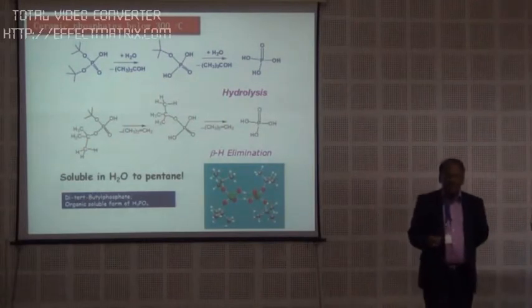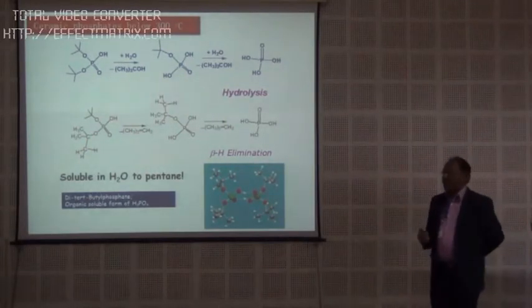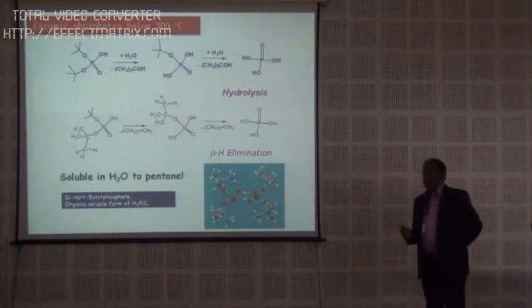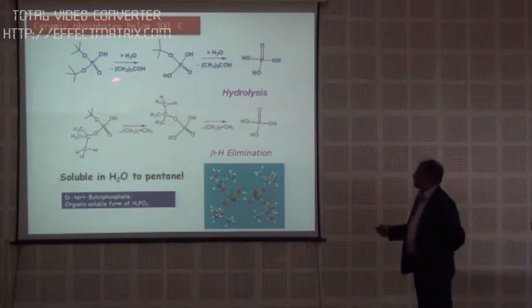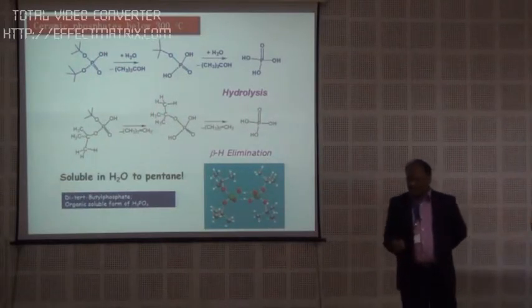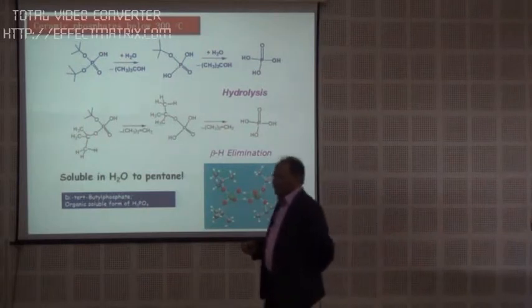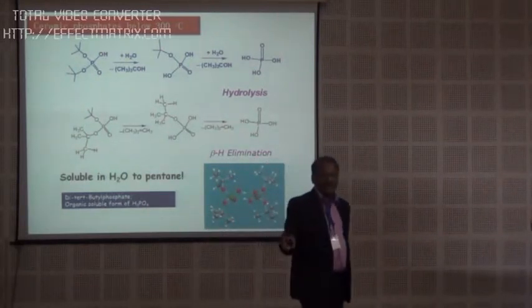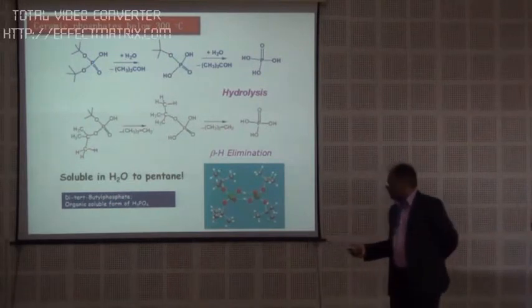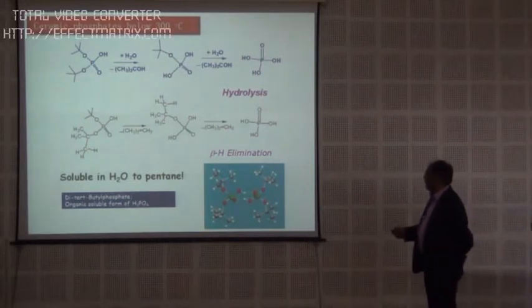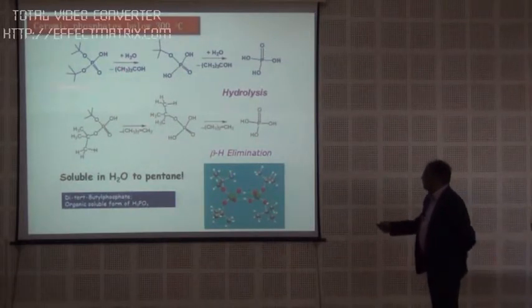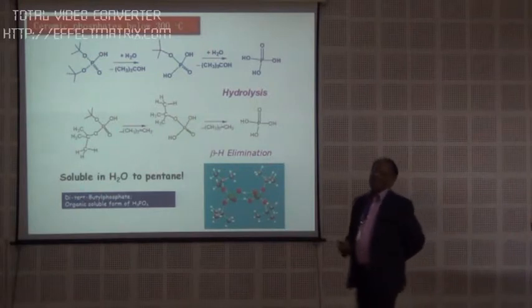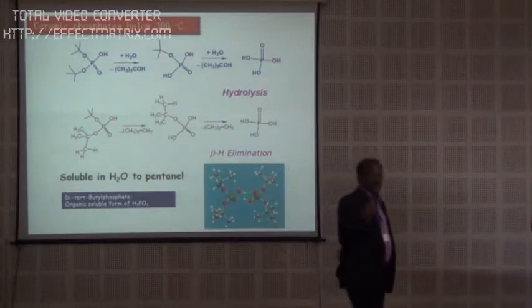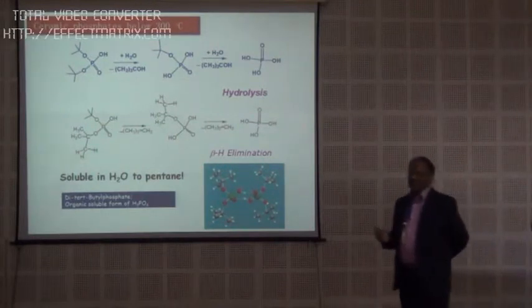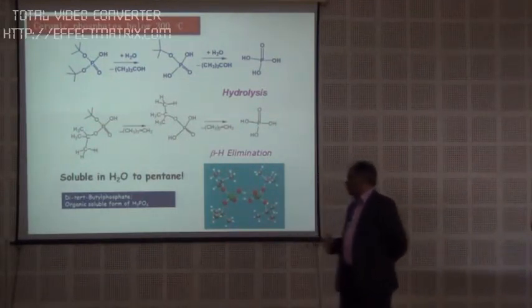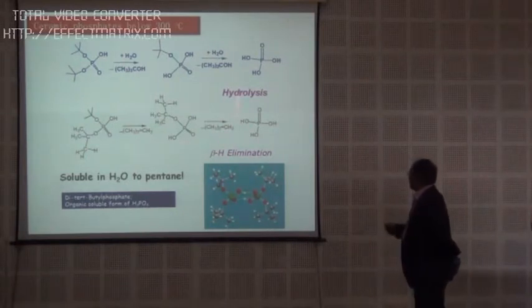Years ago, we recognized that there are compounds in the literature. In fact, a paper published in 1960 by Harris and co-workers in the Journal of the Chemical Society talks about this one particular compound, among many esters that have been described in the paper. This compound was described as useless because you make it and keep it on the table and go for a coffee and come back, you have phosphoric acid. It's thermally unstable. And if you think you're smart and put it in the absence of water, even if you exclude water, it undergoes facile thermolysis or beta hydrogen elimination because it has 9 to 18 beta hydrogens. Any one of these 18 hydrogens can bite back at the phosphorus and form isobutene. As a result, you get phosphoric acid.